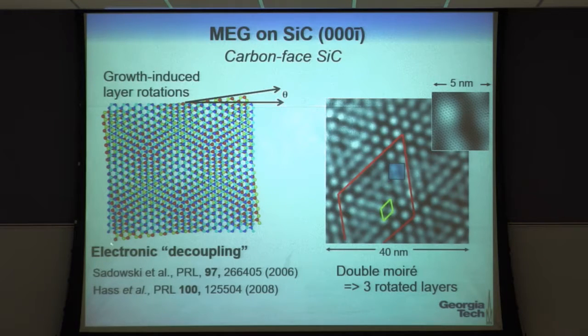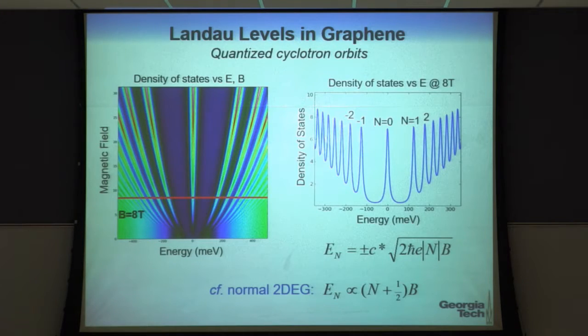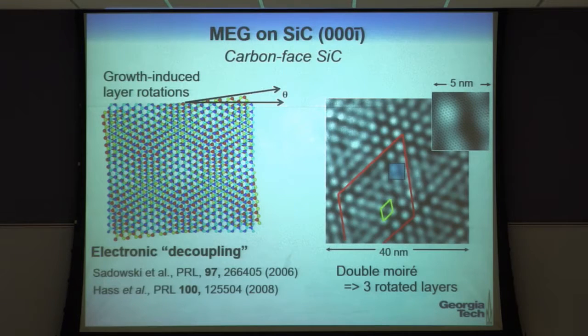And that's what I've tried to denote here with the yellow and red and the blue and blue. There actually, we see two structures here, so we know that we have at least 3 rotated layers. It's a double moire structure. The effect of that is to remove overlaps from one layer to the other between PZ orbitals in one layer to PZ orbitals in the next layer. That decouples, has electronic decoupling of the materials, and as a consequence, I'll show you that the electronic density of states looks a lot like single layer graphene, but what we're studying is the top layer on a stack of about 10 of these rotated layers.